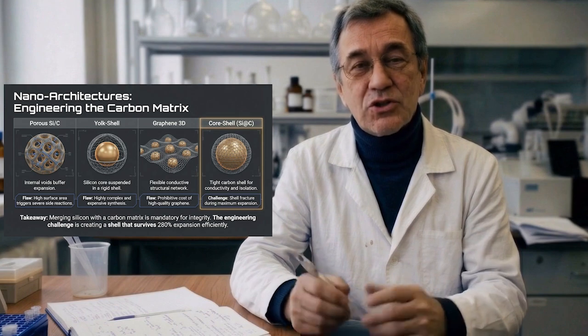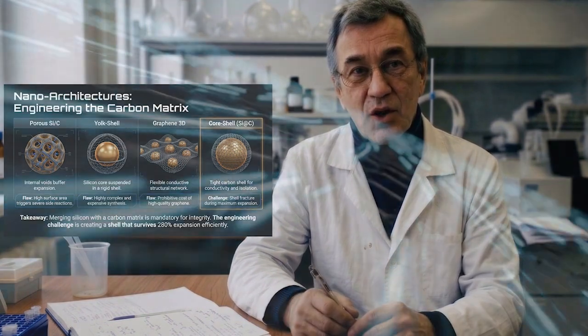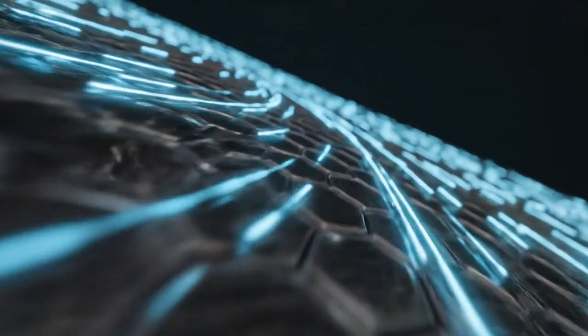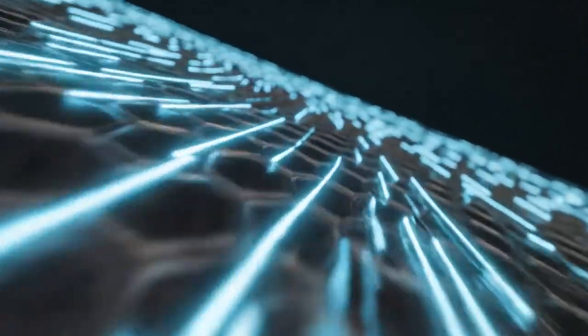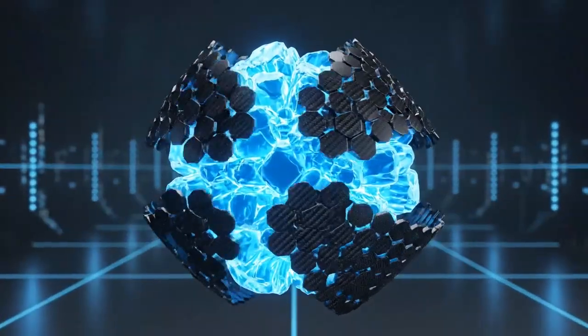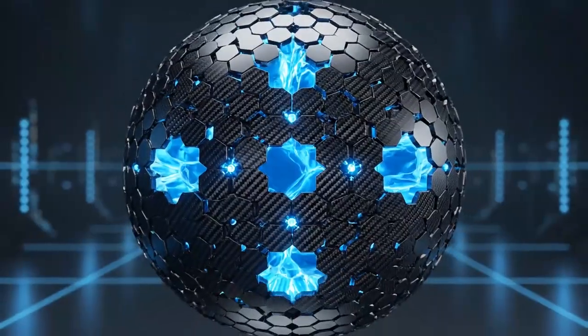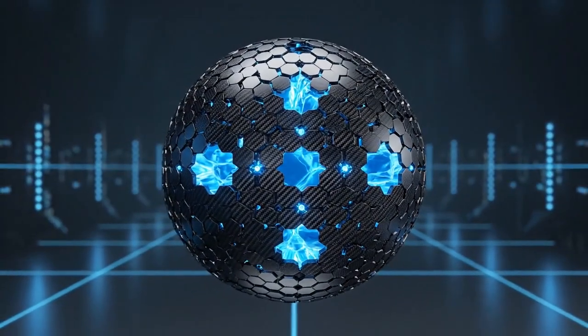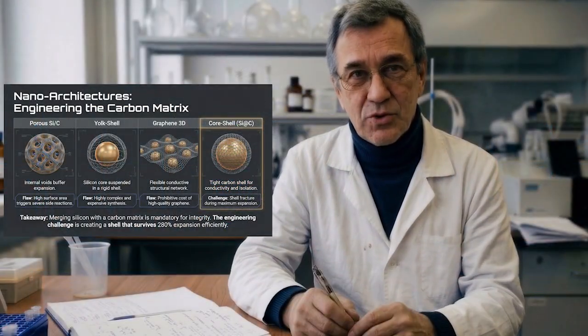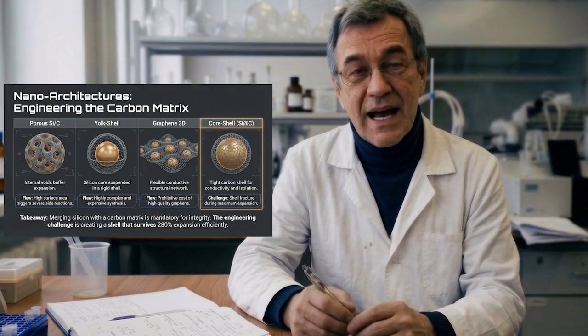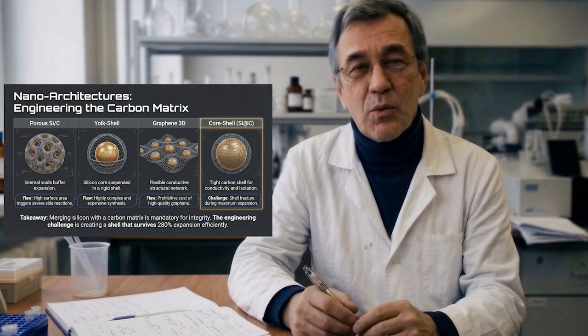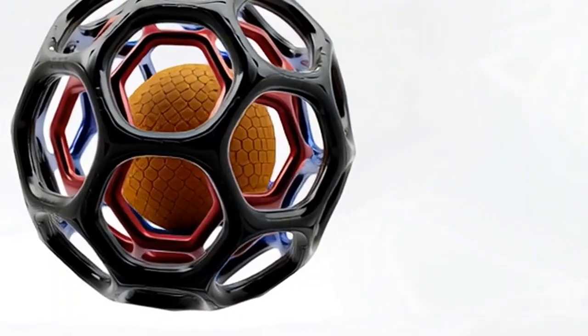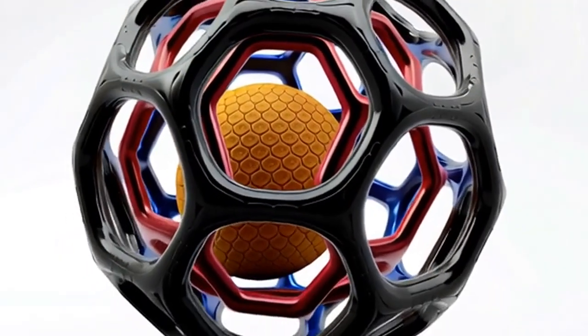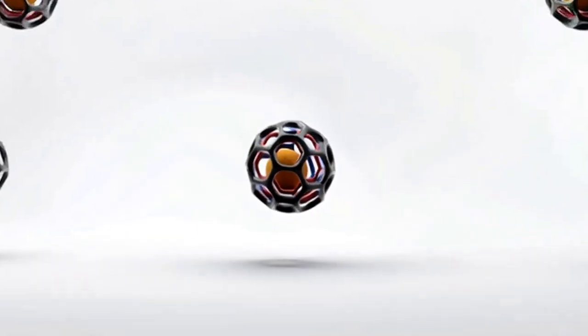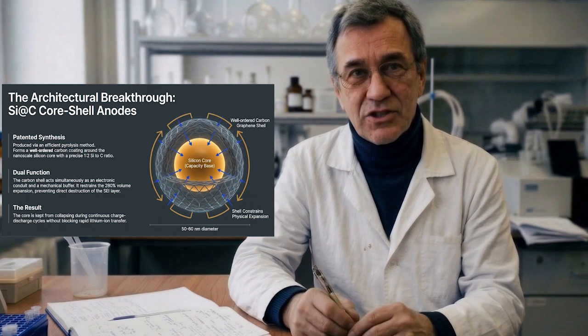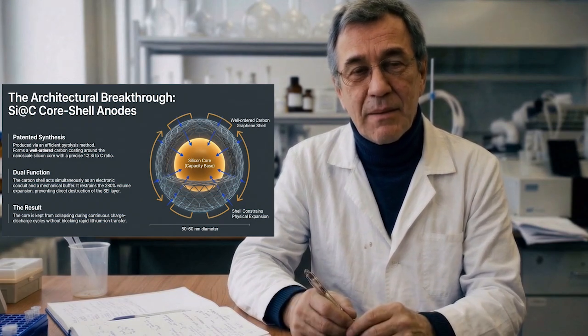This architecture does two critical things. First, the carbon shell provides a conductive pathway, overcoming silicon's poor conductivity. And second, it acts as a physical barrier, containing the expansion of the silicon core and shielding it from direct contact with the electrolyte. This preserves the integrity of the SEI layer on the outer shell, preventing it from repeatedly breaking and reforming. Our silicon-carbon powder, with its brownish-black color and 50 to 60 nanometer particle size, consists of a silicon core tightly bound to a graphene-based shell.